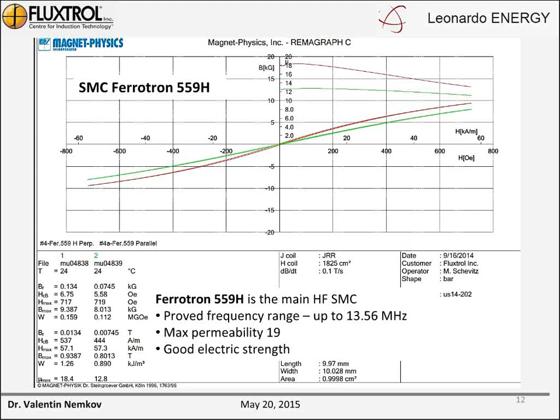Because soft magnetic composites are not so well known by industry, I want to show you two examples of materials. One is Ferrotron 559H, which is a main high frequency material. It can work up to 13.56 megahertz. It has maximum permeability 19. It has good electric strength and may really be called a soft magnetodielectric. You can see that the BH curve is almost linear, and the permeability of this material is almost constant in a wide range of magnetic loadings.